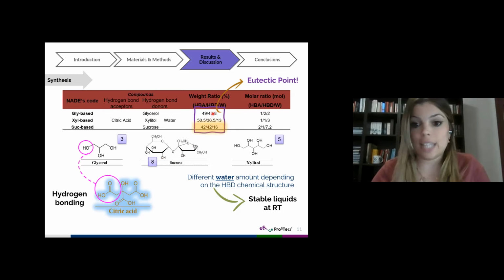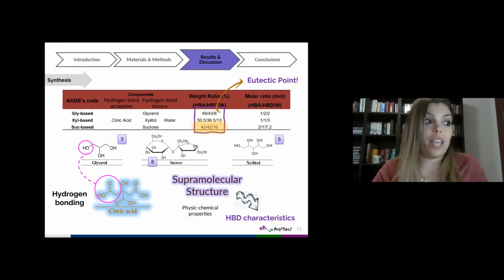This is due to the stronger interaction arising in its microstructural network as a consequence of the high number of hydroxyl groups. Moreover, water allows modulating some properties of this formulation like viscosity or polarity, which also will condition the final properties of the thickened samples. Therefore, a supramolecular structure is obtained in all cases, comprising physicochemical properties that will depend on both water amount and the number of hydroxyl groups forming the hydrogen bond donor components, and will condition the rheological properties of the final formulation after dispersion of epoxidized lignins.